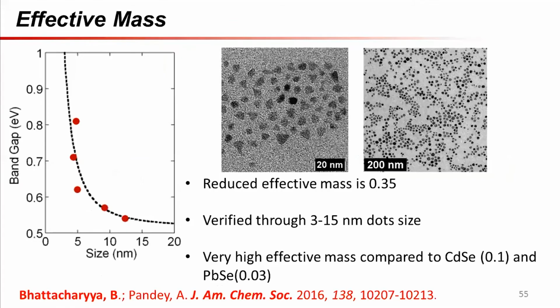Yeah, this one. So what we have here is, you see that as I make the nanocrystal size smaller, the band gap changes, and this can be used as a metric for quantum confinement. And if we fit it with a graph which suggests quantum confinement, then we find also what the reduced effective mass of the system might be. So it's basically measured as a shift in the band gap with respect to the size of the nanoparticle. That's the most convenient way to measure it for pure materials.